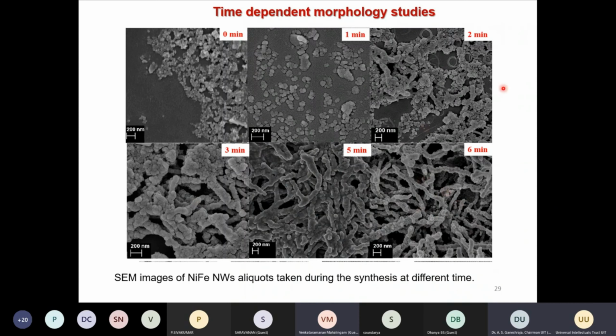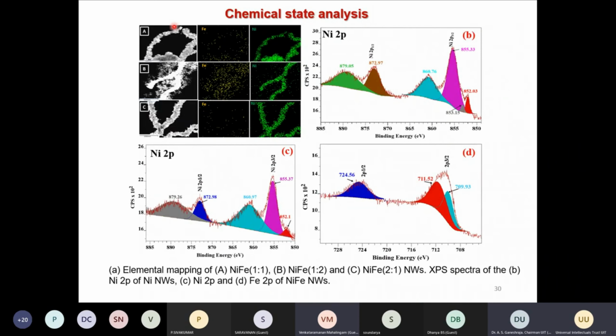So this happens quite fast, but we were able to do this time study, and this is also supported by the uniform distribution of these metals on the surfaces by the EDAX mapping. We have also done XPS to characterize any other phases present, to understand the chemical state of the material. We found that nickel is present, and a small amount of nickel oxide formation is also there.